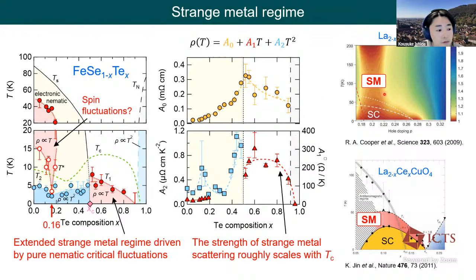This is quite similar to the case of the hole-doped cuprate phase diagram, which is already shown several times in these discussions, and also the electron-doped cuprates. The important aspect of our observation in iron selenium telluride, I believe, is that the pure nematic fluctuation can also drive the extended strange metal regime.